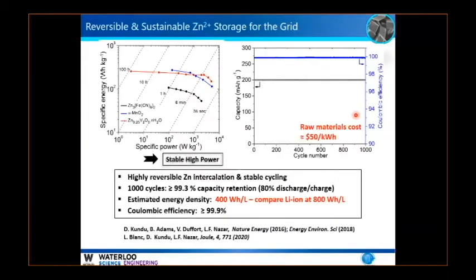And the proof is always in the pudding, so I show here the results of cycling this for 1,000 cycles. We have extremely good capacity, which is effectively flat, and this is real data showing almost 100% Coulombic efficiency with extremely stable response. And this is just a power graph here, which shows the energy versus power. And where you want to be is high energy and high power, and that is what this system provides.